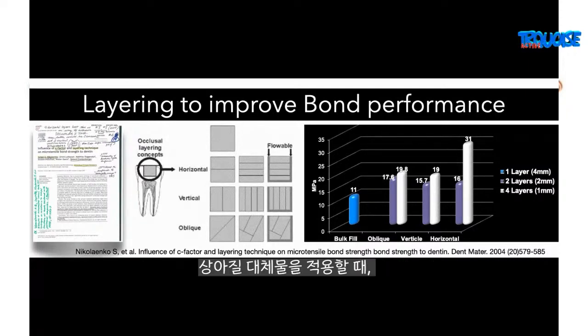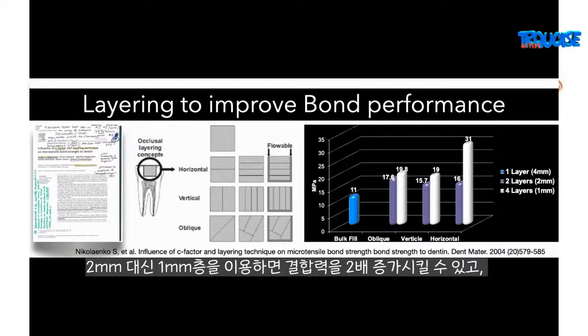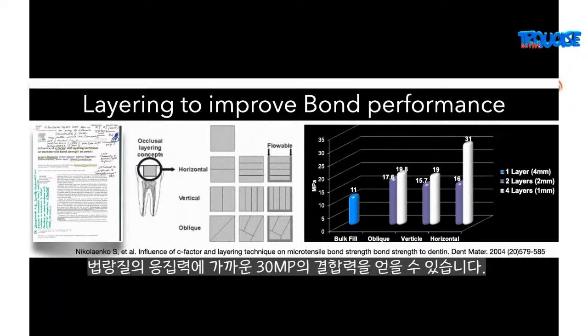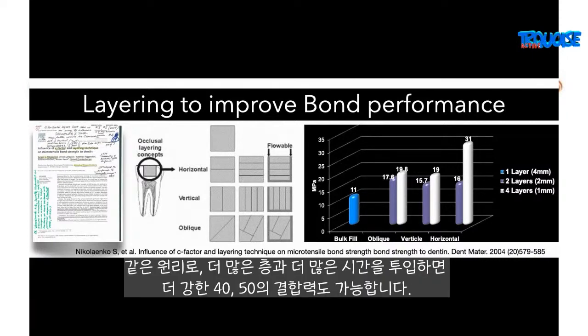So by using 1 millimeter layers in dentin replacements, instead of 2 millimeters, we double the bond strength. And by using 1 millimeter layers instead of bulk filling, we triple the bond strength. And the bond strength now becomes like the cohesive strength of enamel, around 30 megapascals. If we use even more layers and more time, that actually can go to the higher 40s and 50s in bond strength, using the same concepts.